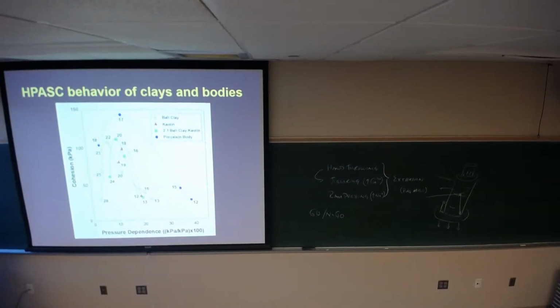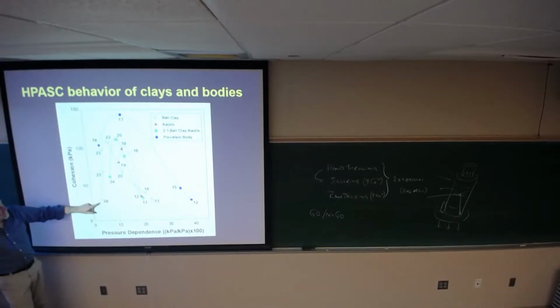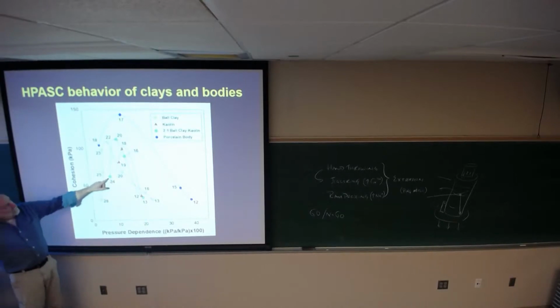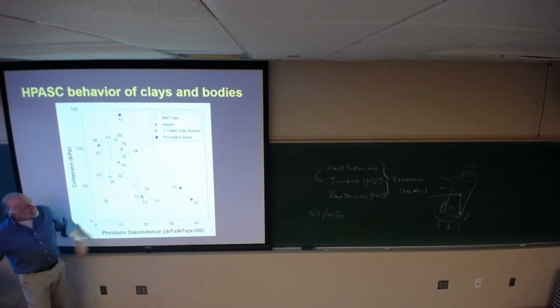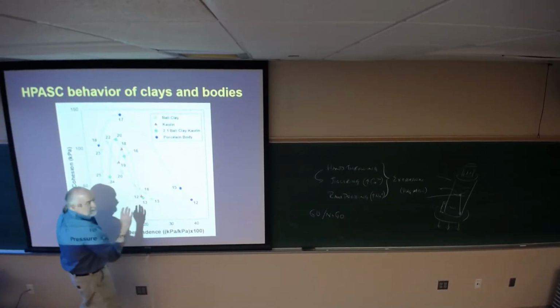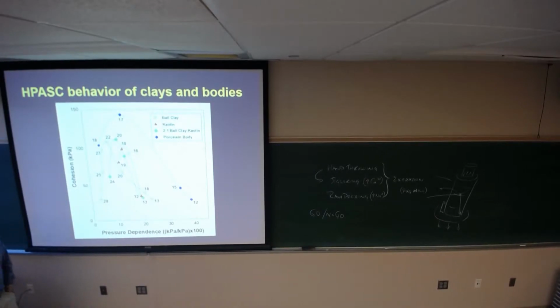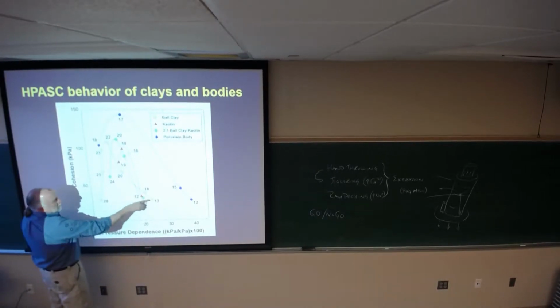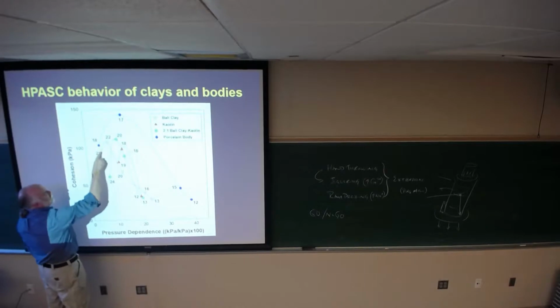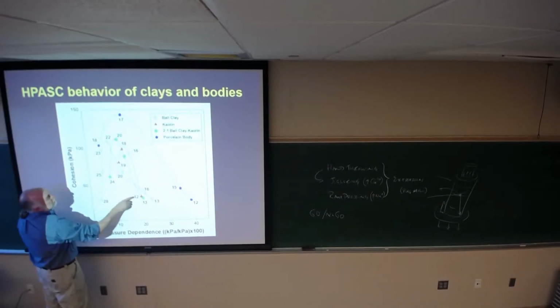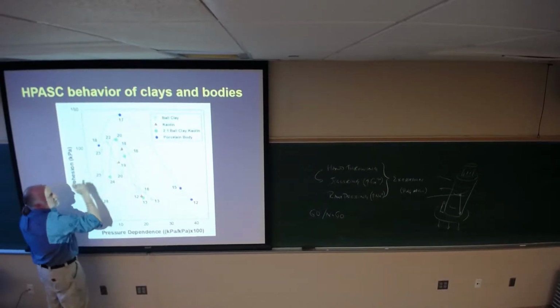But we did learn something else, and that's here, and this has to do with aging. So these are just clays. This is ball clay. This is a mixture of ball clay and kaolin because that was really common. You see kaolin and ball clay mixed. This is kaolin, and then this is actually a porcelain body. And at the time we learned a lot of stuff, but these are water content. So 13, 16, 20, 22, 23. This one is, let's see, 12, 18, 19.